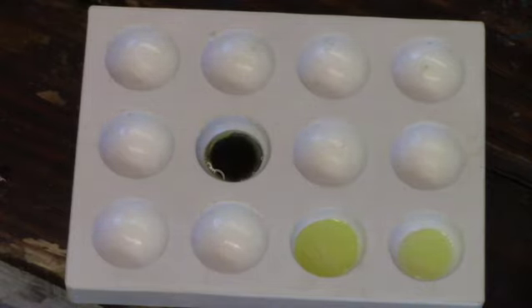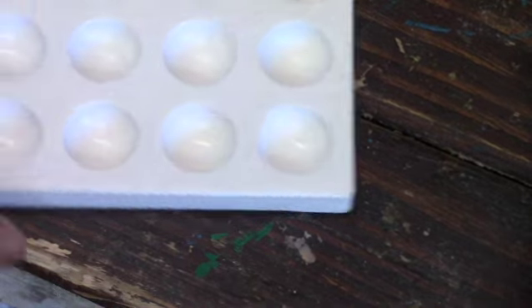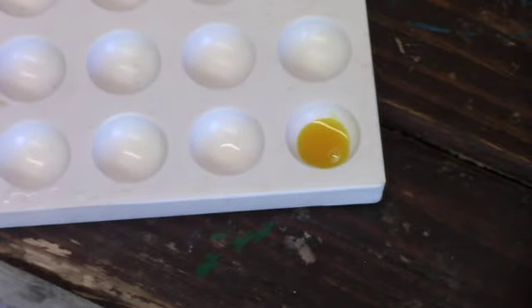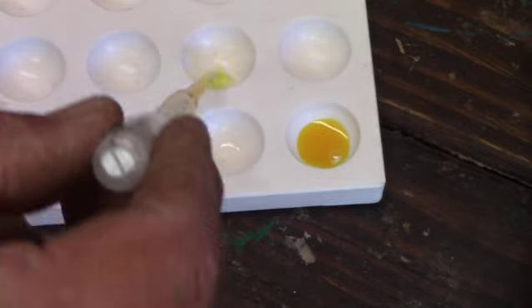So these other two do not make me happy. They have no reaction whatsoever. And if I do stir them, they will turn clear. We're going to take this Stannous chloride test solution out and put it into a separate jar. Once you do a Stannous chloride test and it turns out positive, put that into a separate jar, because you can redissolve the gold and precipitate it properly. You can't get gold once you've done the Stannous chloride test, and it's gold chloride at that point. You can't just melt it back into gold. So you redissolve it in aqua regia and then precipitate it with sodium metabisulfite.